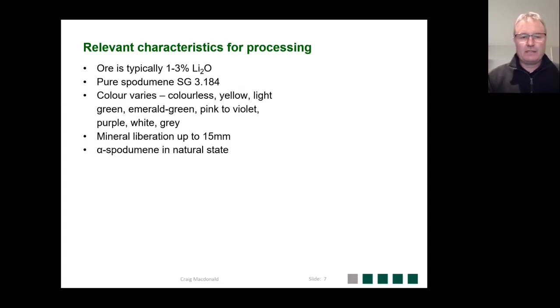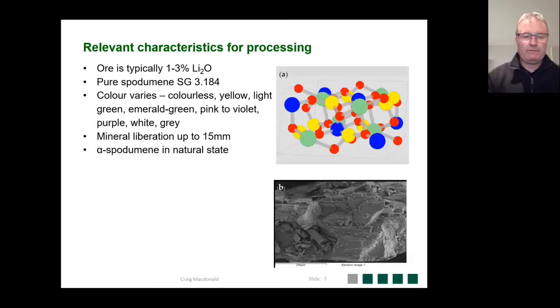In its natural state, the crystals are in what's known as an alpha spodumene. The image on the top right shows the alpha spodumene crystal structure, and for the academically inclined, the green circles are actually lithium. The importance of this is probably more in terms of lithium hydroxide production. What we see in the bottom right is the alpha spodumene in a scanning electron micrograph.